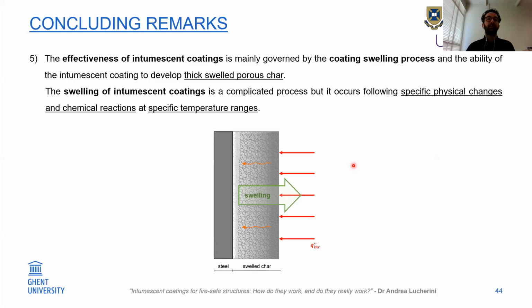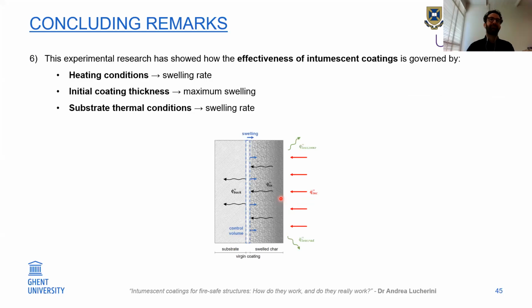The swelling of intumescent coatings is a complicated process, but it occurs following specific physical changes and chemical reactions at specific temperatures that I showed you. When the thermal gradient within the coating changes, so that the virgin coating is at the surface, the coating stops swelling because the concept is completely changed. And finally, through this experimental research, I showed how the effectiveness of intumescent coating is governed by the heating conditions. In particular, it governs the swelling rate.